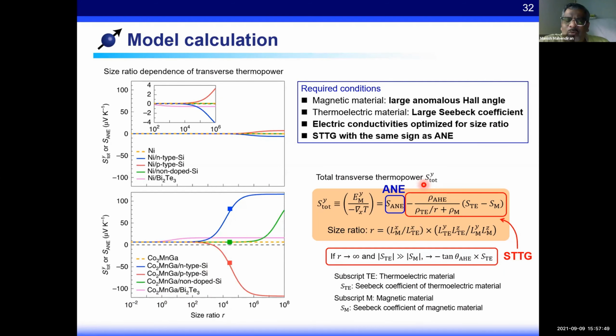Okay, thanks. Just a quick question. What was your initial motivation to choose this cobalt manganese gallium? Was it driven by theory or is it sort of intuitive understanding? Yeah, this is based on the experimental results. The anomalous Nernst effect and Hall effect of cobalt manganese gallium have already been reported. And we know that this material shows a relatively large anomalous Hall angle at room temperature, which is about 10%, much better than standard ferromagnetic materials. So we chose cobalt manganese gallium.